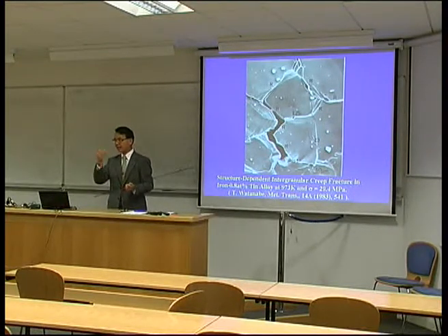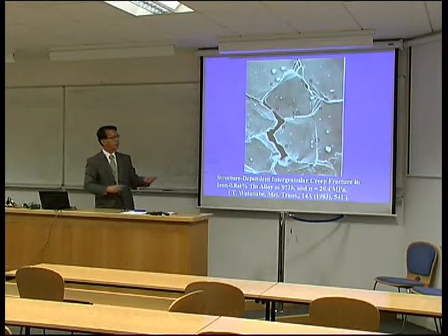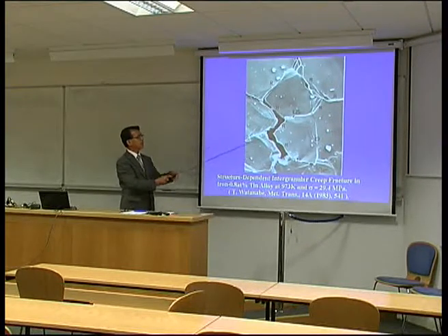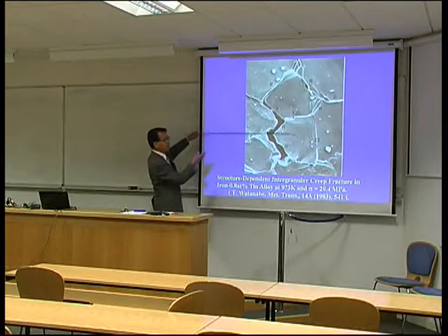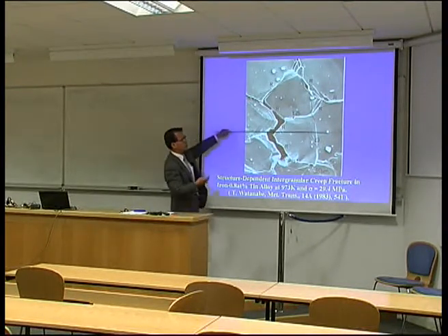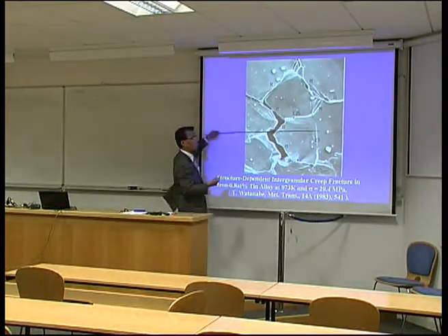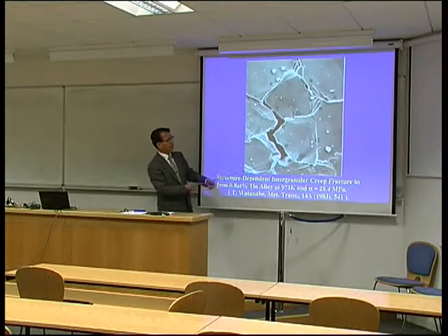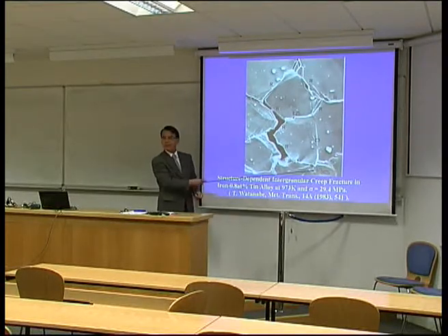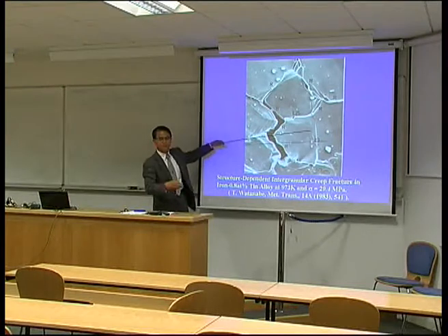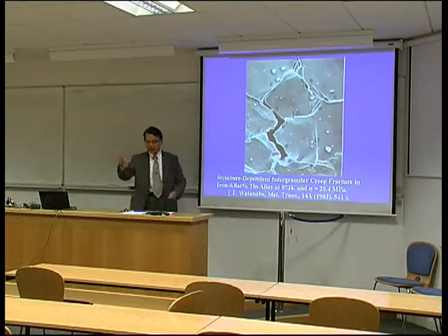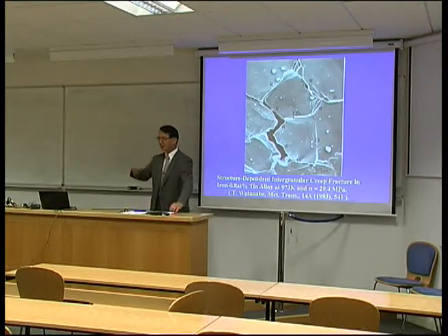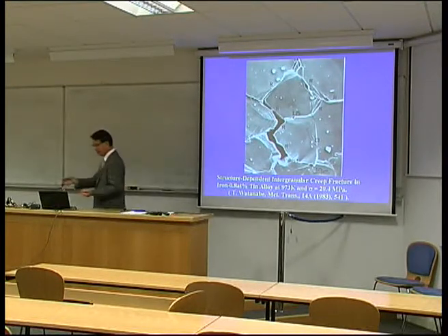Because of cavitation or boundary sliding, fracture will occur in the grain boundary. But actually, in this case, the stress axis direction is horizontal. As you can recognize, a low energy boundary will not break even under the maximum tensile stress like this. So you can see how much effect the boundary character has.